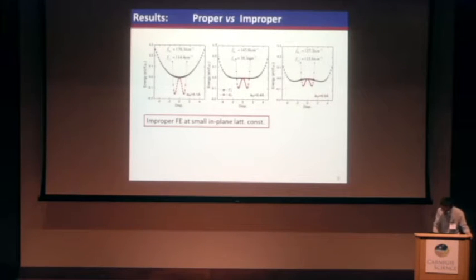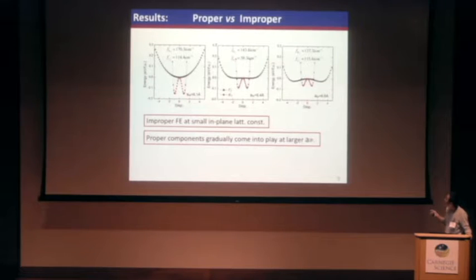Well, when the epitaxial strain becomes larger, we can notice that first the double well of the K3 mode becomes shallow, and then the gamma mode, the bottom of the single well first becomes flat, and then the double well emerges. So that means when the tensile epitaxial strain becomes larger, the polar component gradually comes into play. Yeah, that's quite different and never reported in the yttrium manganite type hexagonal phases.